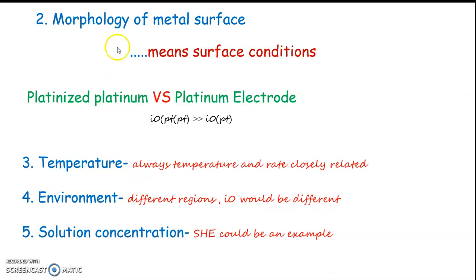The next factor is the morphology of the metal surface, or merely the composition of the metal surface. I can explain with an example. When we use platinized platinum in place of platinum, its I0 becomes large. We always use platinized platinum in the SHE also to produce the best result. Platinized platinum means the platinum electrode is further plated with platinum, which makes its surface more rough and also increases the surface area. It leads to a much higher reaction rate and hence I0 increases further.